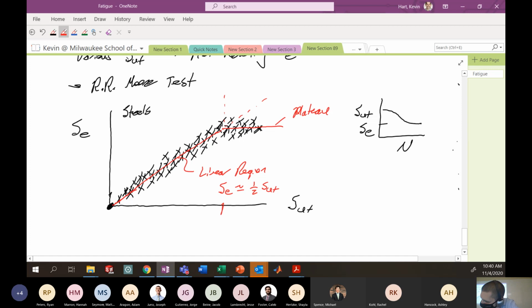This plateau from experiment occurs at about 200 KSI. I think the most recent values that come out, what do they say in the most recent chart? 212 KSI. So up to 212 KSI, your endurance limit is linear. It's about one half of the ultimate tensile strength. So the Y value you're reaching at this plateau is about 106, approximately.